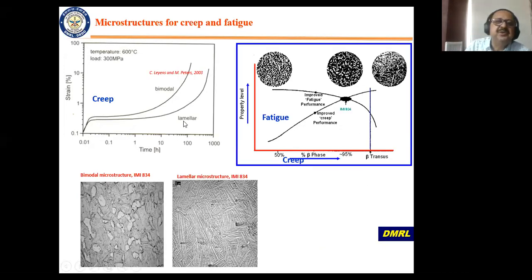Now here I am showing you the comparison of two types of structure and creep. This is a bimodal structure. This is a lamellar structure. As I told you, this is strain and this is time. This is at 600 degrees centigrade and 300 MPa of load. The bimodal structure has lower creep resistance, higher creep deformation, whereas a lamellar structure, that is a beta treated structure, always has good creep properties. This is a lamellar structure of the IMI 834 high temperature titanium alloy, and this is a bimodal structure, which I've shown you. These are optical microstructures.